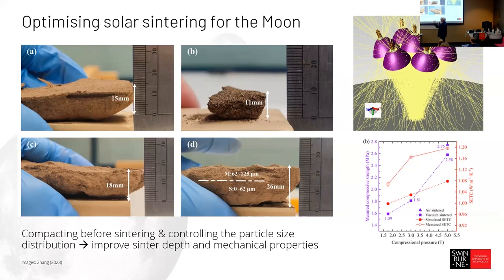And we dramatically improved the strength by putting different combinations of sizes. And we started to get also a thicker sintered material. This is quite important because regolith has very low thermal conductivity. So in other words, it's really hard to get the heat into it. And we're trying to look at a way of being able to sinter large blocks, say to build a launch pad, right? So anyway, Yuan Kun established this very well, and we've got quite good predictive power now of how to sinter these materials. So that was very exciting.